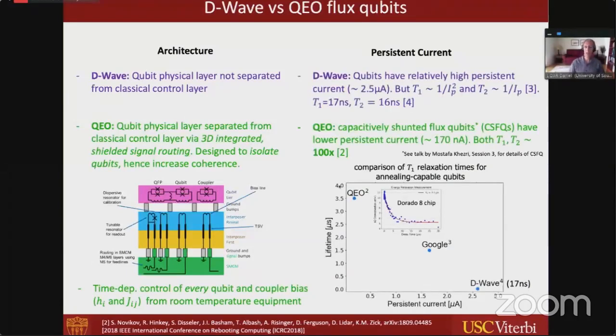As for persistent current, the DWave qubits have a relatively high persistent current, about 2.5 microamps. But a useful heuristic is that the T1 and the T2 times both scale inversely with persistent current. So you'd expect that a high persistent current will lead to a relatively low coherence time. And just recently, we've had a measurement reported of T1 and T2 of about 16, 17 nanoseconds in the DWave qubits. The QEO so-called capacitively shunted flux qubits, the CSFQs, have a lower persistent current by about a factor of 10. And both T1 and T2 have been measured to be about 100 times larger than the ones reported so far by DWave. So here is an example.